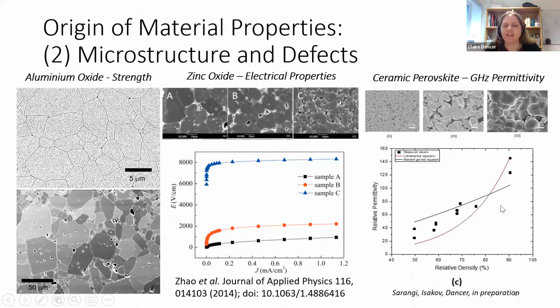But what we've seen is that in these perovskite materials measured in the gigahertz frequency range, we can get quite a radical change in their relative permittivity at microwave frequencies by changing the density of the material. So if we have something that's pretty dense, we do get those high properties which are characteristic of these materials, but we can control that by reducing the porosity down.